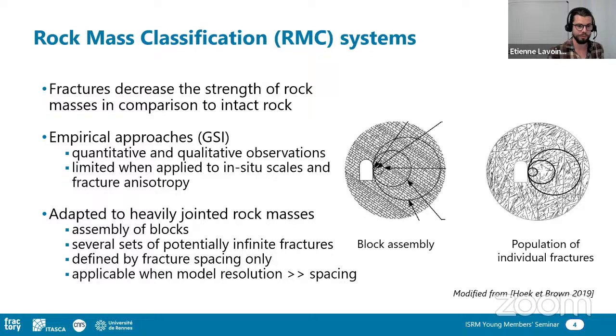And this is adapted to heavily jointed rock mass when you have really a block assembly. So as we can see in the picture on the left, this is a picture that we are all used to seeing. As soon as you have an assembly of blocks made by several sets of potentially infinite fractures, the density of the fracture network is defined by the fracture spacing only. So it is applicable only when the model resolution is larger than this spacing. And then because of this spacing, because of this block assembly, you have the possibility to have a representative elementary volume, which may not be the case in the kind of